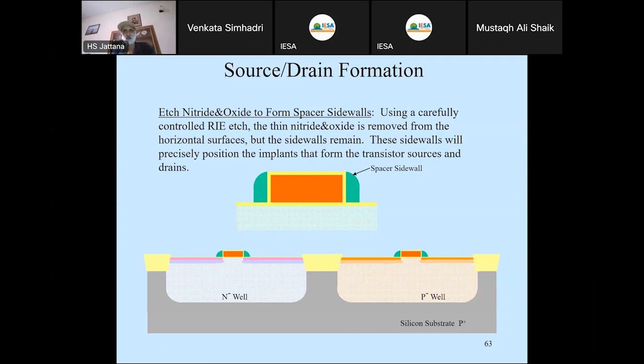So if you add all these things, you will not be able to make a usable transistor if you reduce the geometry beyond 20, because you cannot have a contact of 2 nanometer or a spacer of 1 nanometer kind of thing. You cannot shrink the contact very small. Contact resistance will be very high. You have to make a very deep contact. Aspect ratio will be very, very large, and it's not possible to fabricate uniformly. And the contact sizes cannot be reduced to nanometer kind of thing. And that is how it's not possible to shrink this particular structure beyond 20.